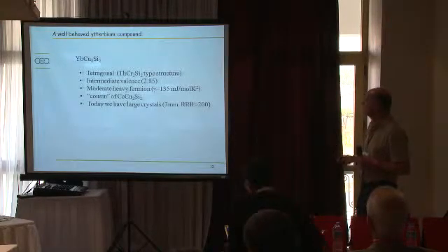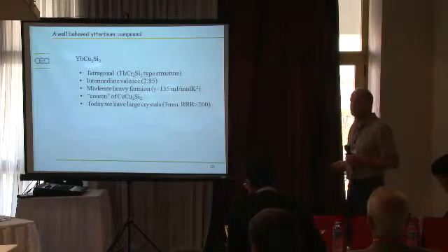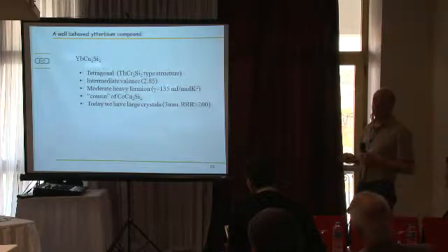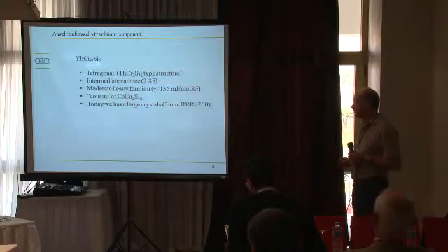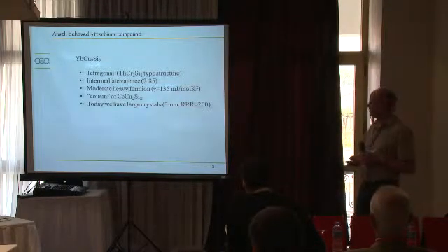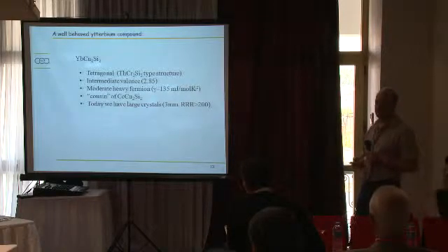Can we find an ytterbium system which behaves as we expect? Yes. So YbCu2Si2 seems to be the ideal system to study. It has a common tetragonal structure. It is an intermediate valence, but not too far from the ytterbium 3+, a moderate heavy fermion. It has good breeding because it's obviously related to the very famous series CeCu2Si2. And importantly, we have today very good crystals.